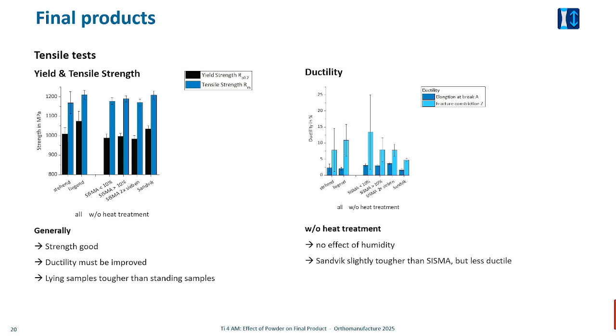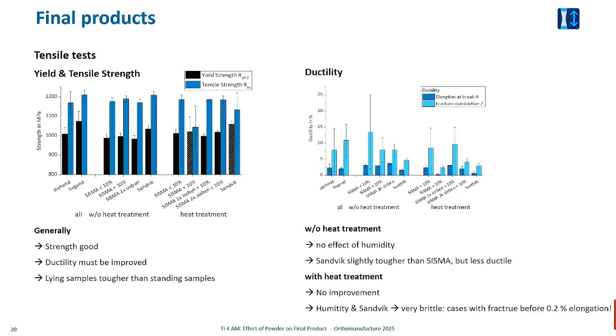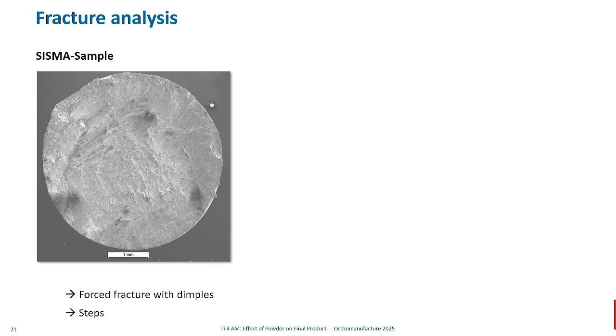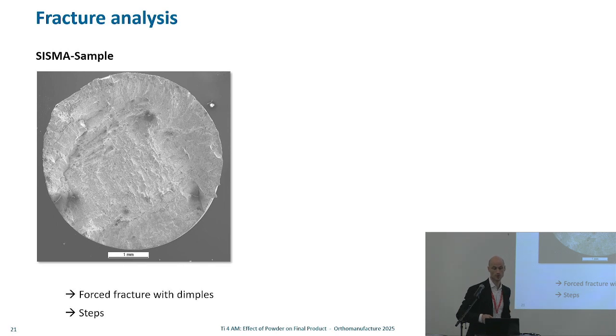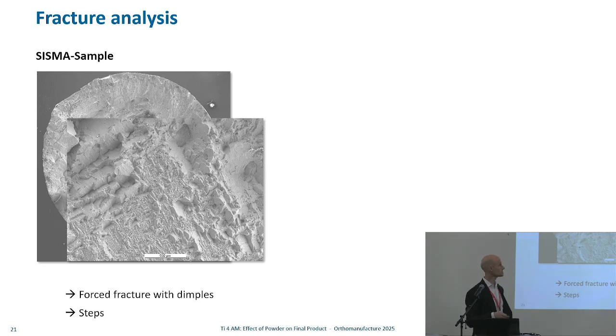So we do not have kind of homogeneous material properties at the end. The ductility was not ideal in these samples, even with the heat treatment. The heat treatment did not change too much in ductility in this case. But this is an old project and development has been going on. After all, we can do the fracture analysis to look at the fracture surfaces in detail.